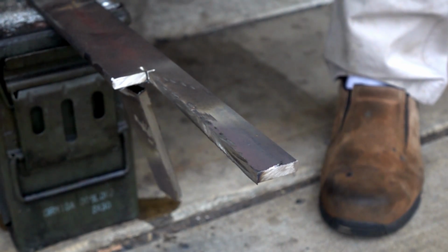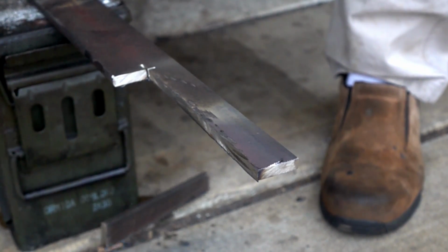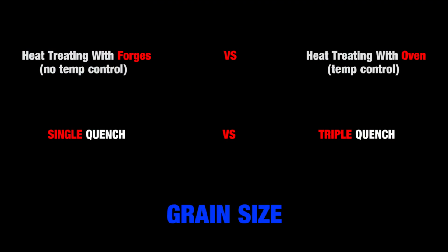My objective will be twofold. First, I want to compare heat treat and quenches done with a forge to heat treatment accomplished with a temperature-controlled oven. I've done this experiment with hypereutectoid steels, and the difference is impressive, by the way. The second is to see if triple quenching is superior to single quenching, and if so, perhaps it can make up any deficiency forgeside quenching has when compared to using a temperature-controlled oven, for example.